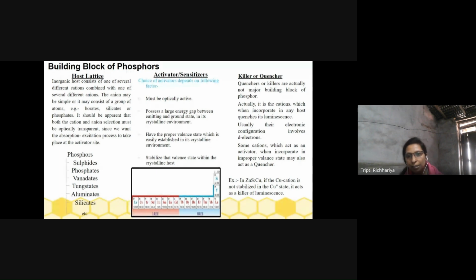The other one is the killers or quenchers of luminescence. As we have discussed in the choice of activators, sometimes many dopants, when doped in an improper host lattice, instead of enhancing the luminescence properties, act as quenchers or killers of luminescence. That means they diminish the luminescence properties of that particular host lattice by creating an energy sink, so that the absorbed energy is released non-radiatively without releasing the energy in the visible region.